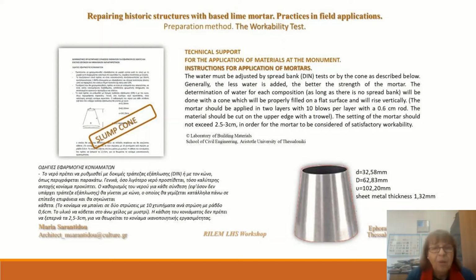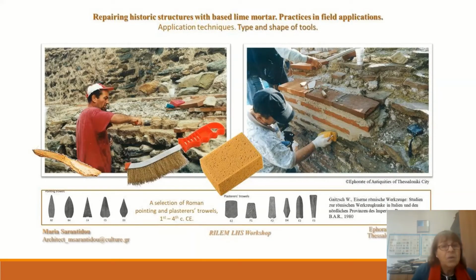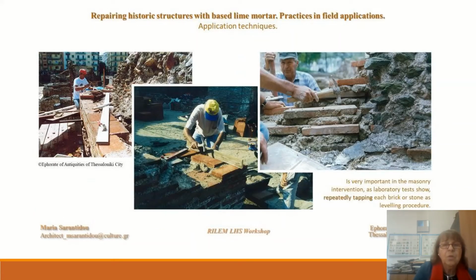Here is an example of what we have proposed: a slump-type cone in order to find the water demand for adequate workability on site. There are also other particularities which are important for application. We need specific tools, for example. We also need to compact very well, otherwise we lose up to 50% of the strength and also adhesion.